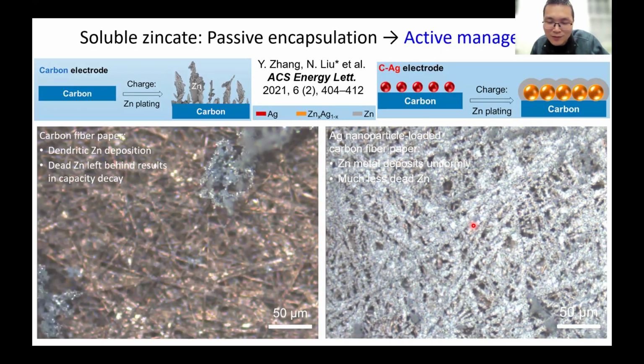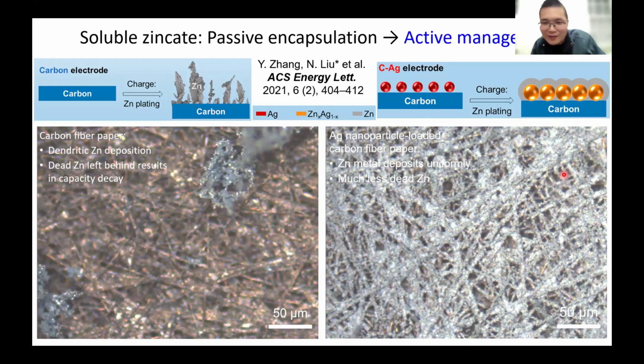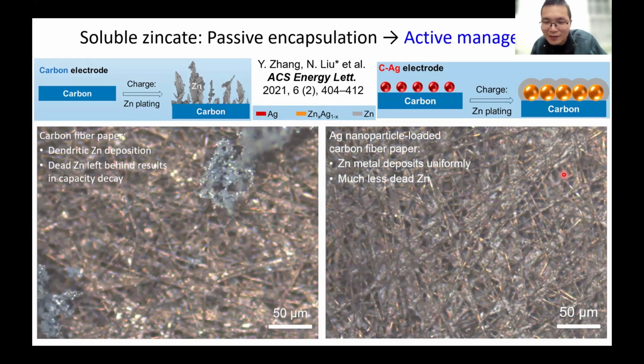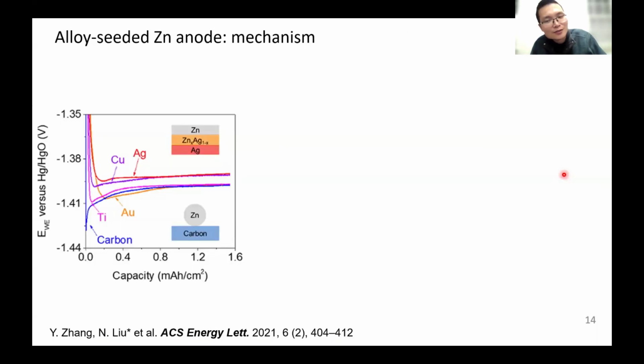You can see now with the silver, the deposition is much more uniform. There is no dendritic structure. And when you switch the current to stripping, it also disappears uniformly. There is no dead zinc and it is very uniform. So silver can spatially control where the zinc deposits. Here is the reason. If you just have carbon, then zinc deposition has to cross a nucleation barrier. But if you have silver, because it can alloy with zinc, the barrier is much lower. So if you have both silver and carbon, the zinc will prefer to deposit on the silver first.